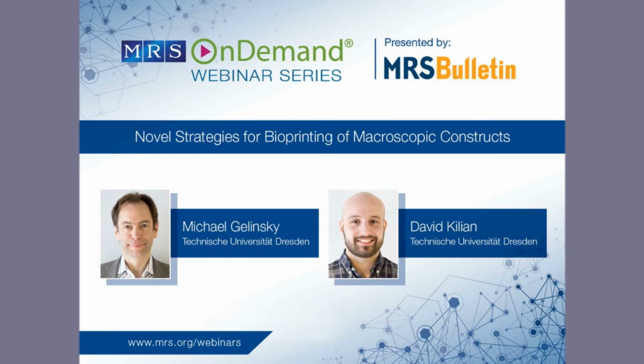Yeah, sure. So basically, as introduced in the talk, this shear thinning behavior is one of the most critical and most important factors or aspects for extrusion-based bioprinting, since this basically means that when increasing the shear stress or shear rate on some material, the viscosity basically decreases. So when bringing together those materials, you end up with some non-Newtonian behavior basically. So viscosity decreases as the shear rate increases, basically due to the reorganization of the polymer chains in there. So they are more stretched in terms of this and less entangled maybe. So when thinking about the actual nozzle that we extrude the material through, they're kind of less viscous and are extrudable in that case.